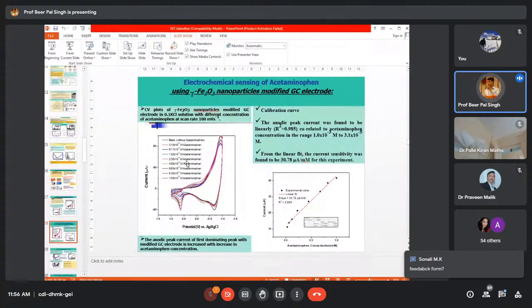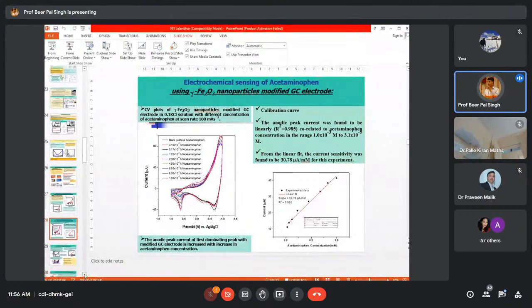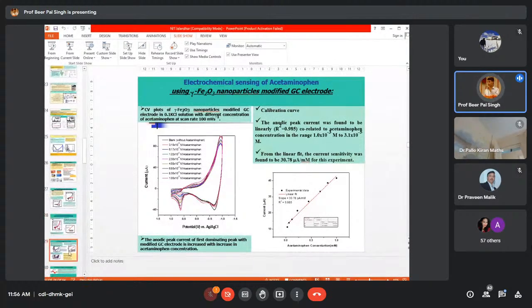And you are seeing over here that we start our experiment from 10 to the power minus 3 mol acetaminophen concentration, and we go up to 10 to the power minus 5 mol acetaminophen concentration, which is very close to micromole. And we found that there is a linear relationship between the anodic peak current and the acetaminophen concentration. And by that idea, we claim that we can easily sense very small amounts of acetaminophen by using this particular material. As time is short, I will move fast.